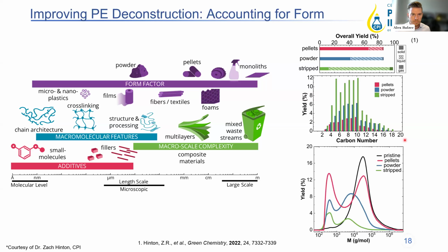And we also saw similar trends in the solids that came out of this, in that in the same fashion that we saw higher liquid yields of something like a powdered HDPE, the intact HDPE that also existed in these solids was lower than that of the pellets. So kind of confirming the same sort of diffusion limited mass transfer problem.